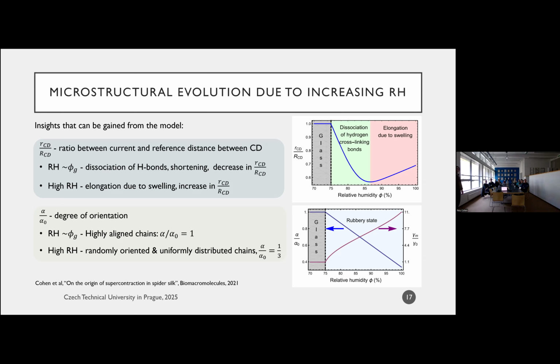And it turns out that the reason why we get this stretching here is due to swelling. So in the classical swelling of gels, if I have a gel and it swells, typically the chains in the gel have to stretch to make room for the water molecules, to accommodate the water molecules that diffuse in. In this region here, I don't have to accommodate them because I'm relieving the constraints on the chains, right? And so I get loss of orientation, I get dilation, but the chain itself contracts. Once I get to this point, I've broken most of the intermolecular bonds that restrict the mobility of the chain. And now the chain starts to stretch a little bit to make room for the water. And we also did a very similar analysis with the orientation, and we can measure how the orientation gets lost. Okay, so based off of this, I hope I've convinced you, we understand why supercontraction happens.